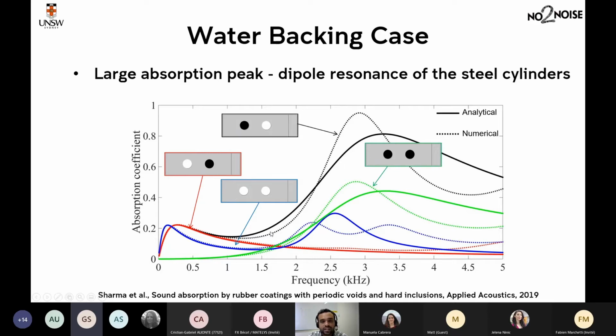However, when you have this case where you have a layer of hard inclusions followed by a layer of voided inclusions, you see that there's a peak of really high sound absorption. And this is because this layer of voided inclusions reduces the stiffness, and that means at dipole resonance, the hard inclusions can oscillate at a larger amplitude because the stiffness here is smaller, right? And that leads to this peak of very high sound absorption.